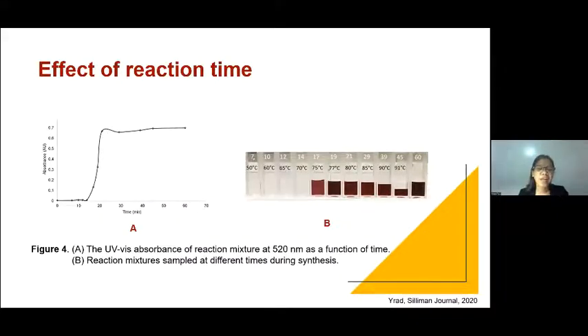The absorbance of the reaction mixture at 520 was monitored and plotted against time. Figure A shows that absorbance at 520 increased with time. The absorbance reached a maximum at 21 minutes and made a plateau thereafter. This is consistent with previous reports. Further heating up to 1 hour did not produce significant change in the absorbance at 520 nanometer. Therefore, based on these findings, heating time was set at 1 hour.